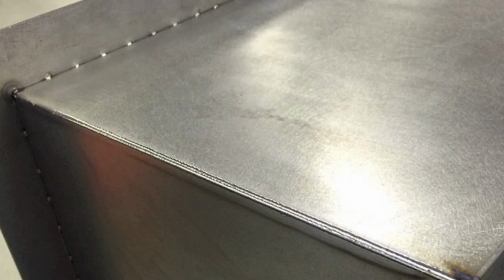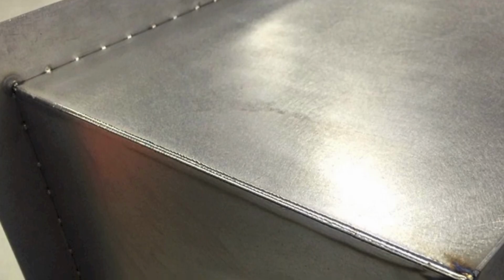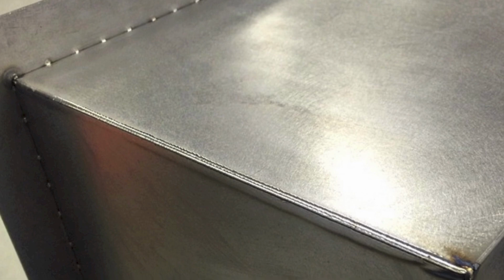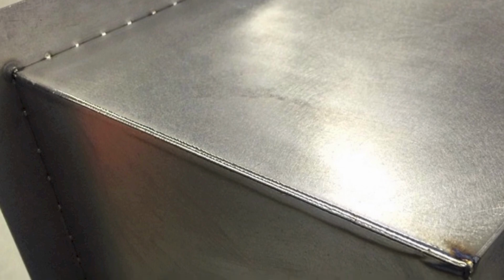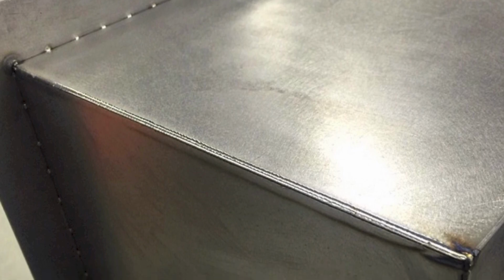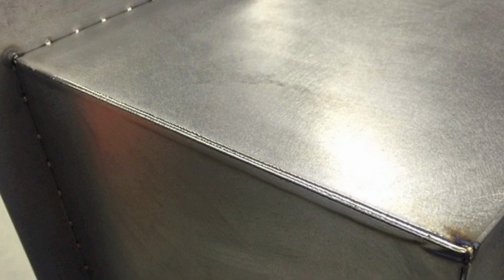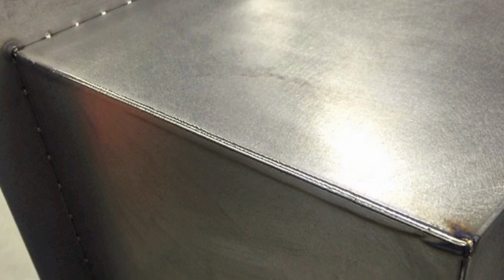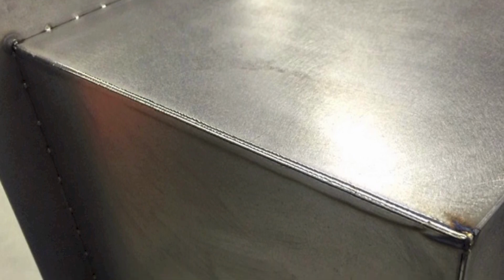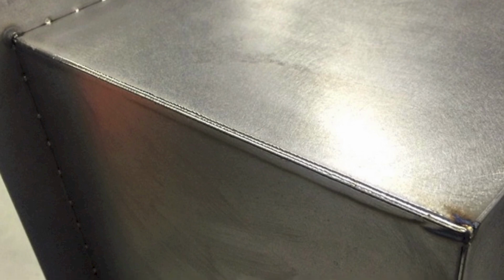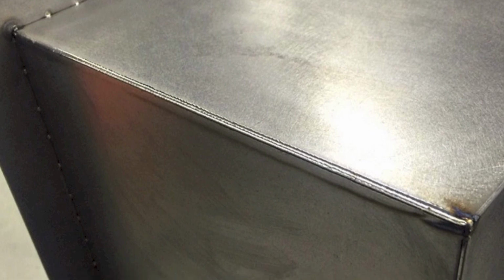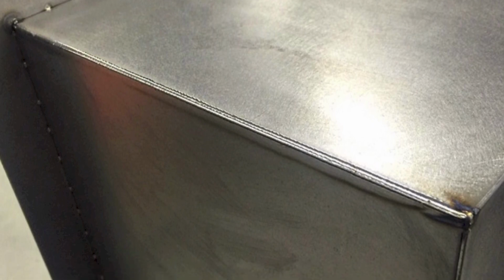I can usually use that technique and have 16-gauge come out basically warpage-free. And actually, a lot of these things, pans and stuff like that, once I get done welding them, if I sight down them and look at the reflection, the only warpage is where I tacked them when I didn't have my chill element set up. And so it kind of shows how much the pulse settings can keep warpage down.